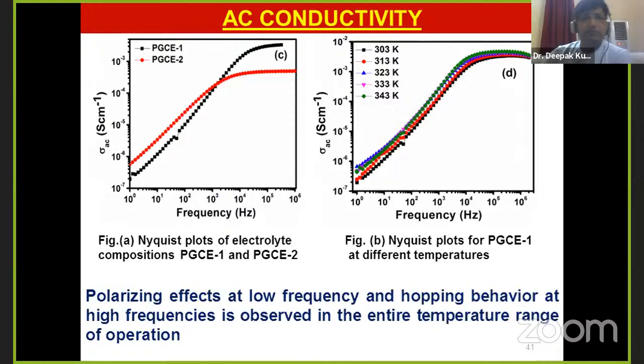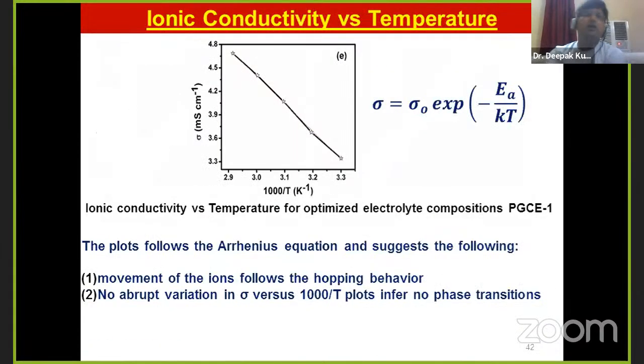At the same time, if we move to the higher frequencies, then the conductivity saturates and polarizing effects subside. At different temperatures, we have also seen that the conductivity follows a similar pattern. However, the conductivity has enhanced slightly. We have also measured conductivity as a function of temperature, and we can see that conductivity follows the Arrhenius behavior, which indicates the movement of ions via hopping behavior. And since no abrupt variations are shown, it means there are no phase transitions occurring.